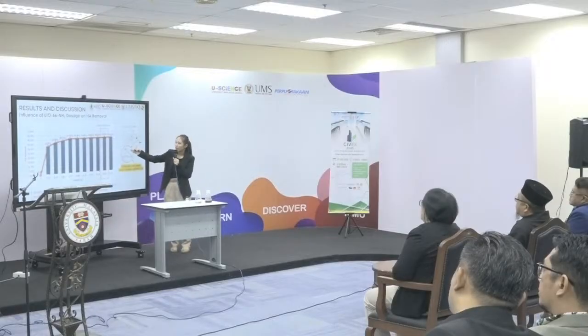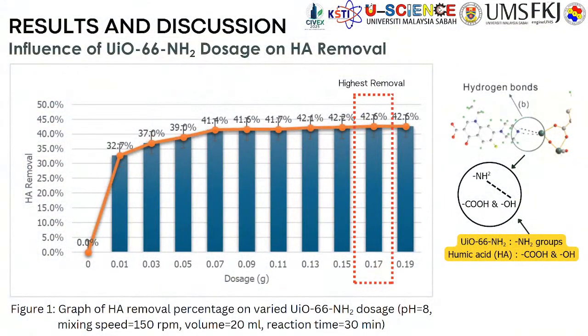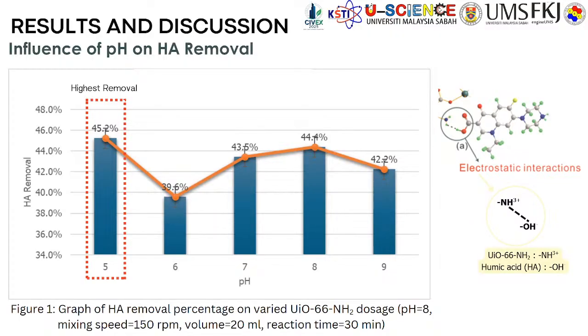Okay, thank you for the question, Dean of Faculty. So for dosage, we have found that the mechanism is hydrogen bonding between NH2 of the UiO-66-NH2 and the COOH and OH groups of humic acid. While for the effects of pH, it is due to electrostatic attraction between the negatively charged humic acid and the positively charged UiO-66-NH2, which is NH3+ and OH-. They will have attraction. That's my answer.